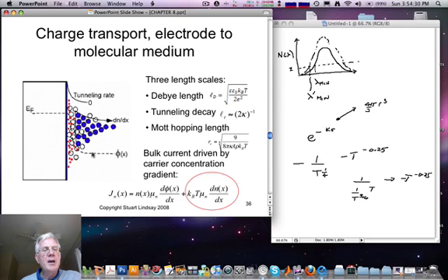However, if the electric potential is now constant in the solid, i.e. the electric field is zero, there is no electric driving force for current in the solid. Nonetheless, current still occurs because of the concentration gradient built up as carriers accumulate near the electrode. The equation that captures these factors is the so-called Nernst-Planck equation, shown here for current density.